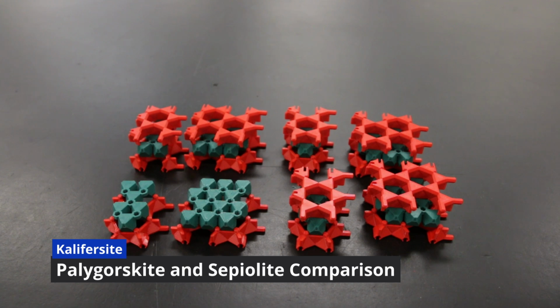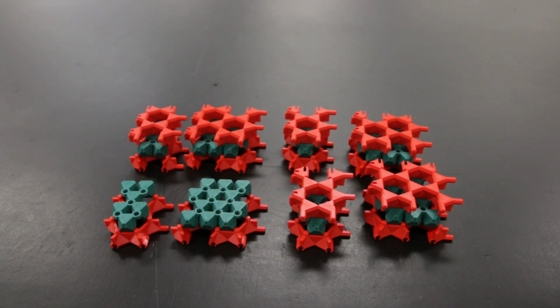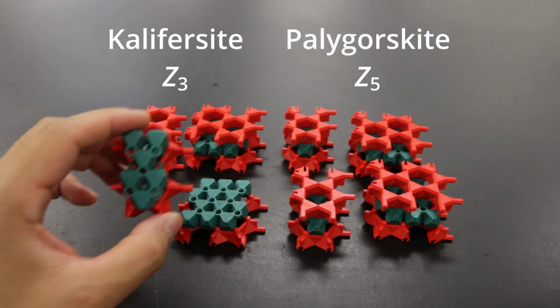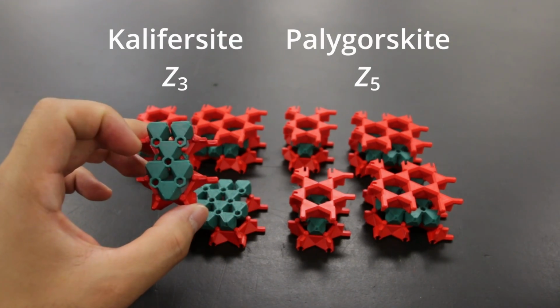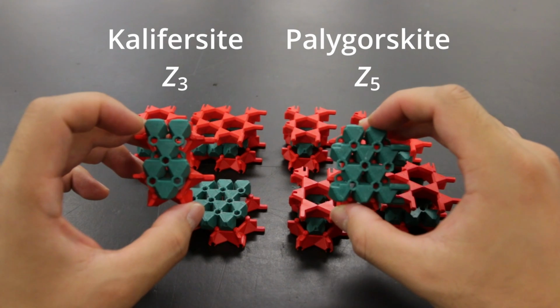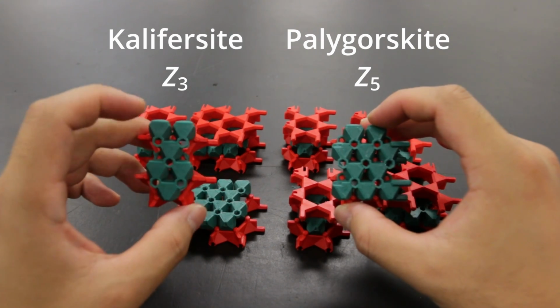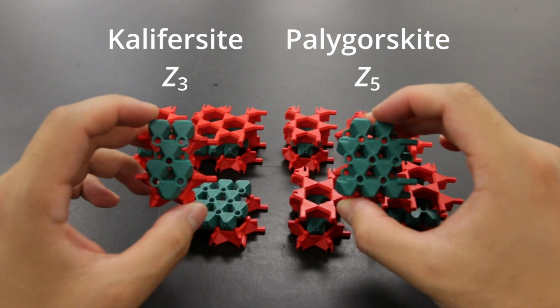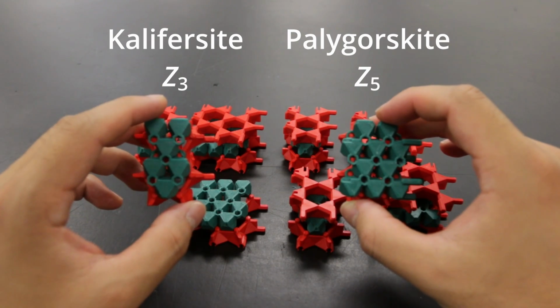There are differences between the modules in Kalifersite versus those of palygorskite and sepiolite. For example, in the double chain sections, we see that there's a site missing, so compare that to that of palygorskite. And so instead of getting the typical Z5 module that we get in palygorskite, we get a Z3 module.